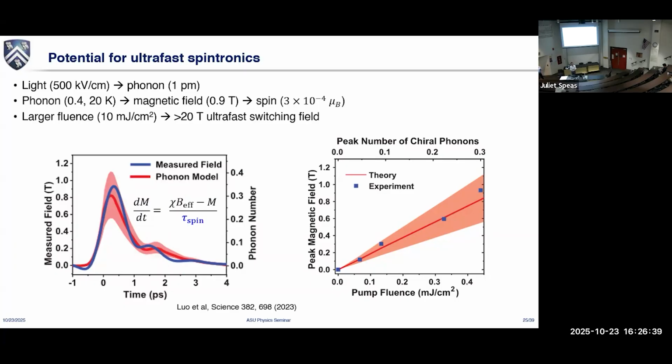What degrees of magnetization do you get? Yes. So in this work, it's tiny. The reason is this material is a paramagnet, and the amount of spin generated by a given field also depends on how long the field's duration. If it's a pulsed field, yes, it's big, but then most of the spins do not have time to respond. Also, this is relatively high temperature. The lower the temperature, the more susceptibility of the spin. So technically, yes, we can push the amount of spin bigger, but in this case, it's not very large.